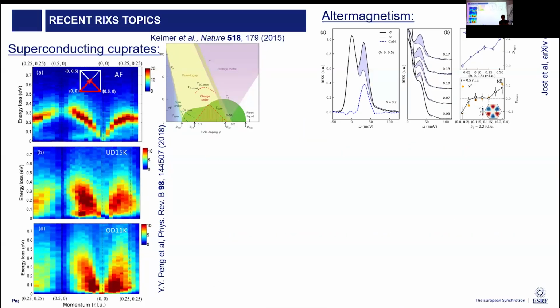We would expect Raman-like transitions for the DD charge transfer as well as anything intraorbital. The problem with the maps that I showed is we have contributions from phonons and magnons, and that's giving a bulge and a distortion onto the elastic line. One of the questions we have about this material is whether or not it's negative charge transfer. So what you're seeing in that region is the absence of a band gap. And this is very strange.